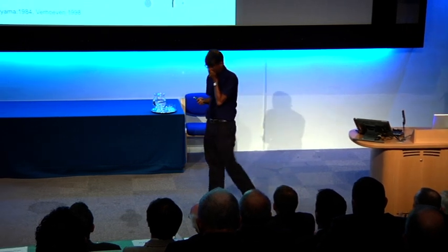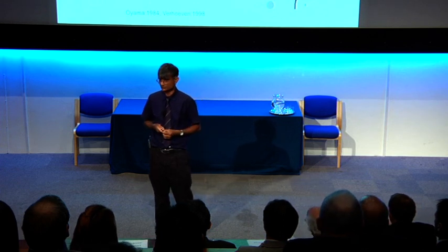So we've done work in the department which is the most rigorous theory for the pearlite transformation. It doesn't assume that the pearlite grows by diffusion in the parent phase, or by diffusion in the boundary, or by diffusion in the ferrite. Any diffusion path is possible, and whatever the system chooses depends on the circumstances. So by doing that, we've got a rigorous theory for the pearlite reaction, and the theory for this reaction has been available for some time.